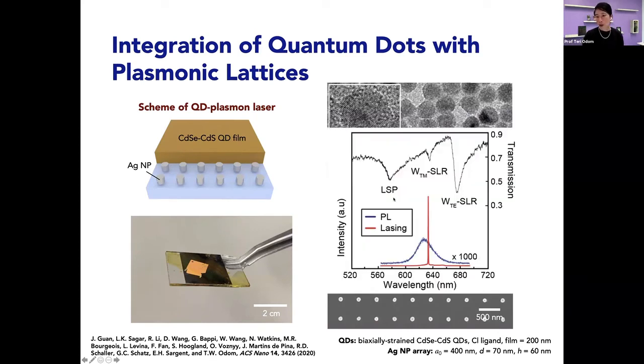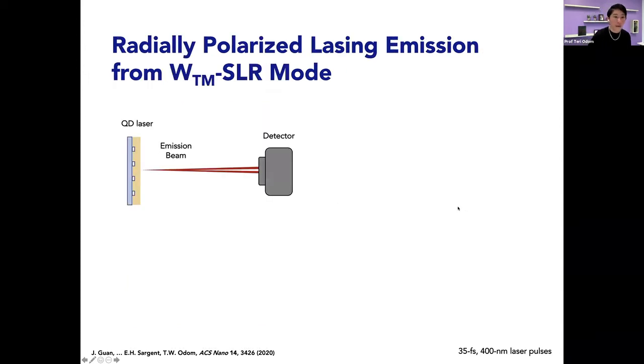And you'll notice that there are a couple of different resonances here. So this is the photoluminescence in blue of the quantum dot emission, and we achieve lasing in the middle of it, but it's due to what is called a waveguide SLR. And the reason why we have these new types of hybrid modes is that the colloidal nanoparticle film has a relatively high index. So we no longer have a pure SLR, but we have an SLR hybridized with a waveguide. This is waveguide TM, waveguide TE mode. And so we're interested in looking at what the polarization properties of the emission looks like.